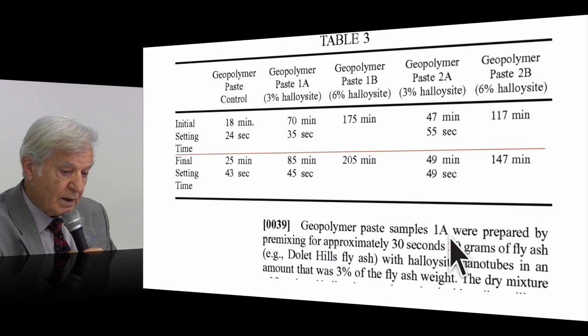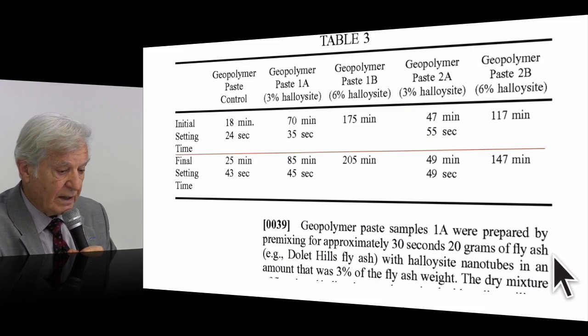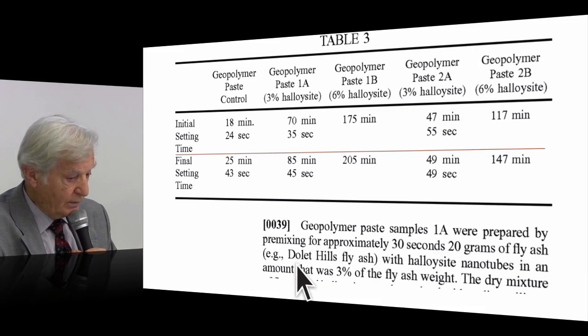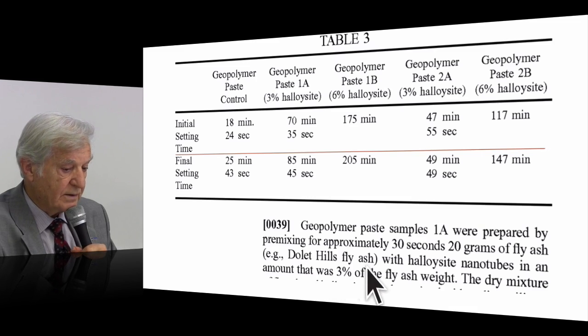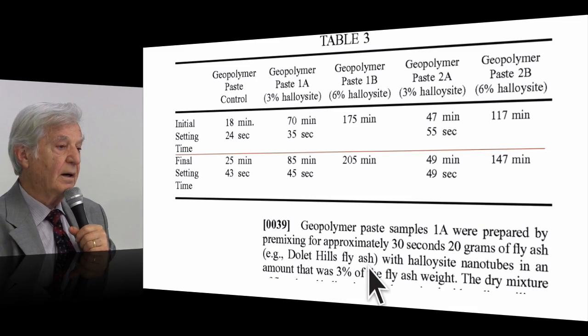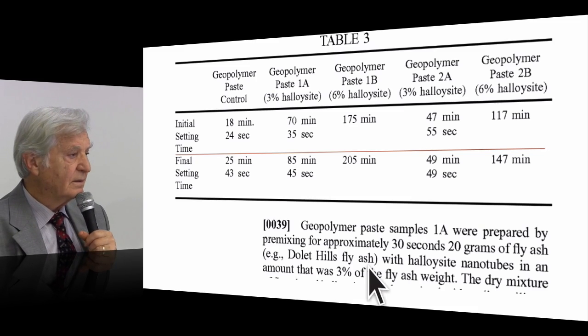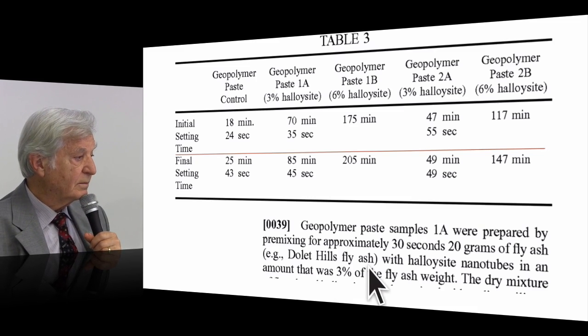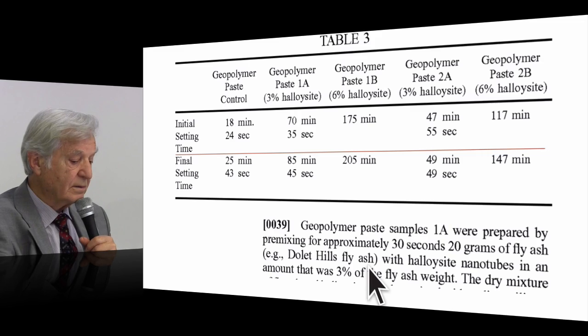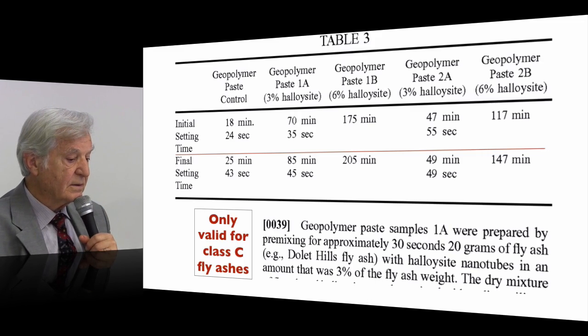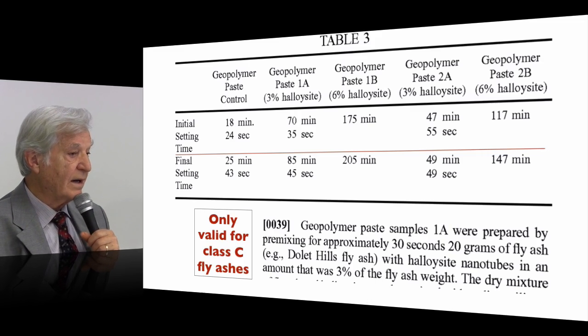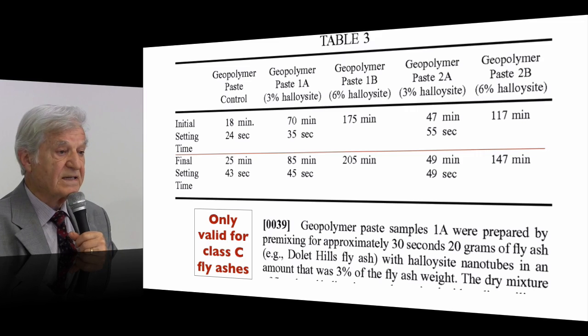Geopolymer paste samples were prepared with premixing for approximately 30 seconds 20 grams of fly ash. Example, Dolet Hills fly ash. What is that? Ask Google, and Google gave the answer. This is a class C fly ash, the class C with a high amount of calcium oxide. We know that it flash sets.